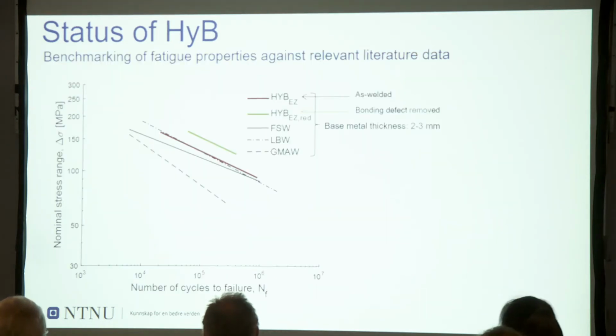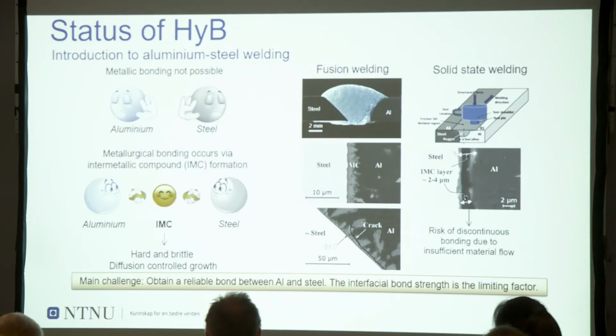If you compare from the literature HyB with different other techniques, which is the green line here and the red line here, it is evident that we have a strong advantage of HyB. The comparison is made taking into account the range of thickness that we have used for the test. So also for friction stir welding and gas metal arc welding, we are considering welding of 2-3 millimeters.